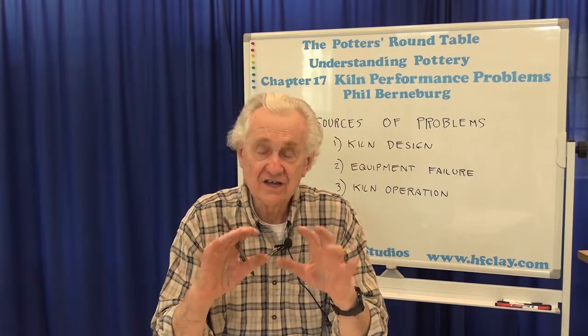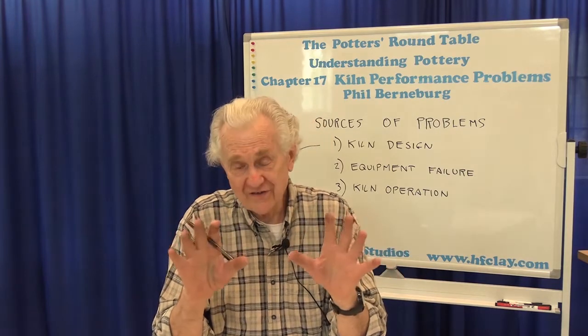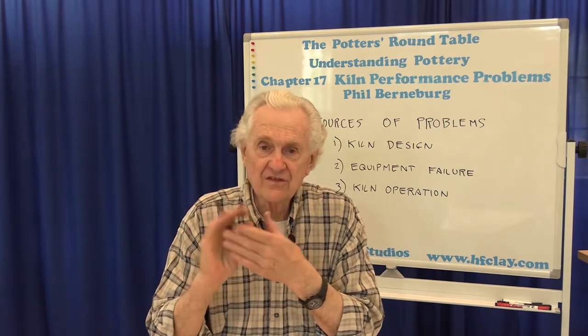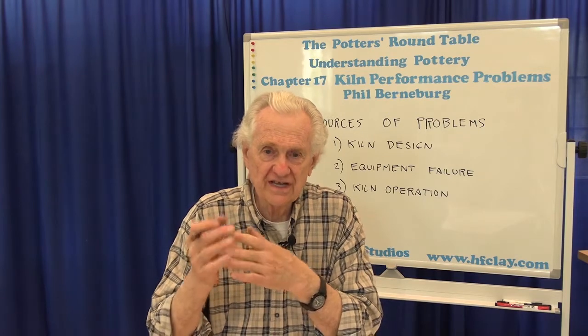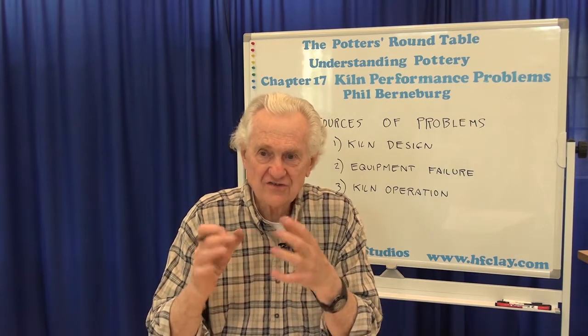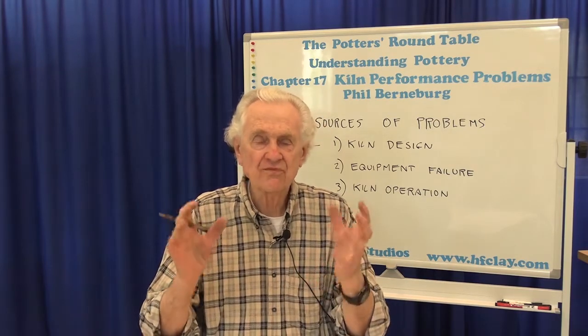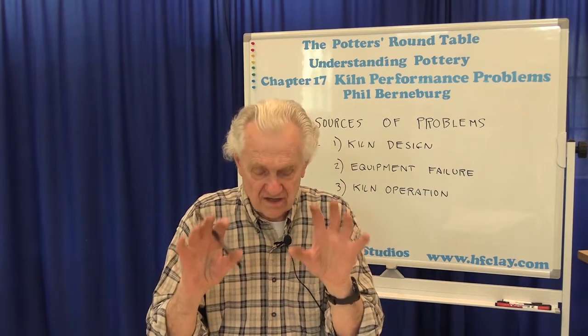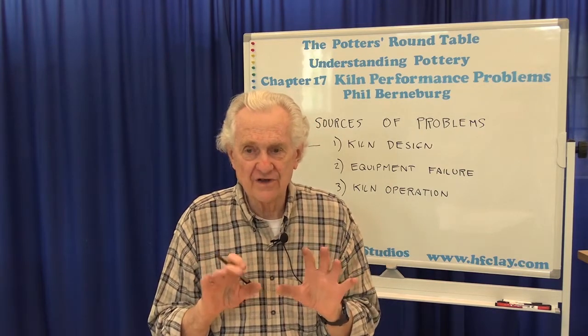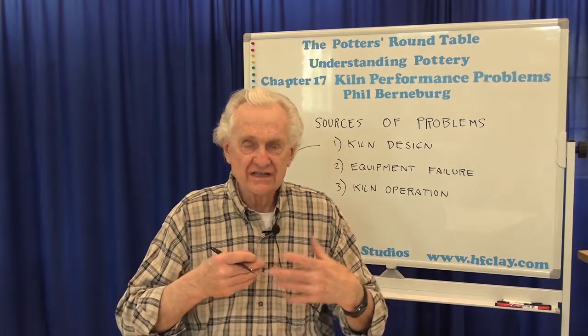Unmelted ash on pots, basically, you end up with the firing and you've got this crusty looking volcanic lava. Some people like this, but you don't, let's say. Well, it could mean that you didn't reach enough temperature, you didn't get hot enough to actually melt the ash, so that the pots got sticky and the ash stuck to them, but not enough to melt. Or it could be that you produced ash too late in the firing. You may have gotten enough temperature, but if you're making a lot of ash late in the firing, there simply may not be enough time for it to melt.